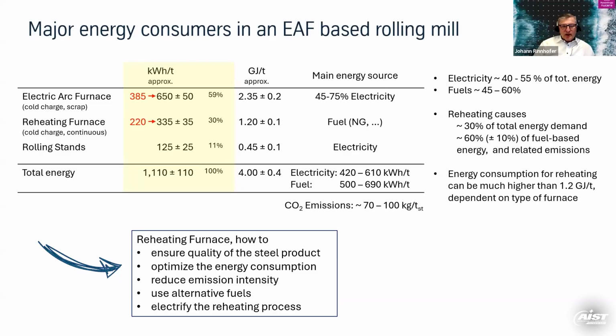In the end, we will have CO2 emissions of 70 to 100 kilos per ton of steel by burning fuels, when you use natural gas. This doesn't sound like a lot because in a blast furnace operated mill, we have around 2 tons of CO2 for 1 ton of steel. On the other hand, a reheating furnace is very easy to measure.